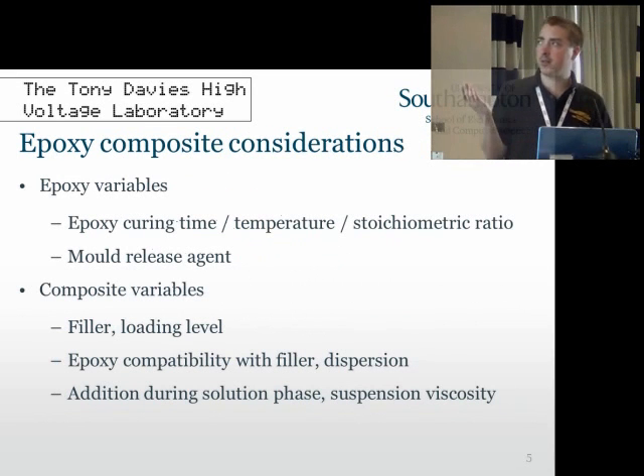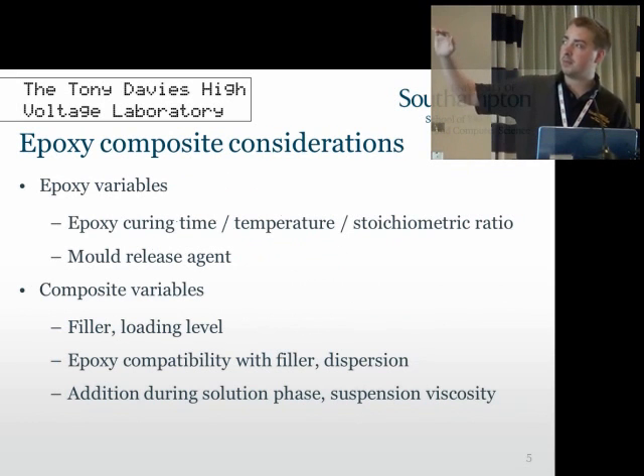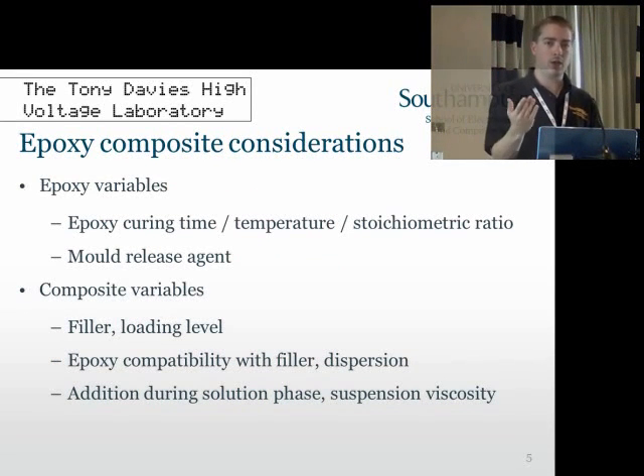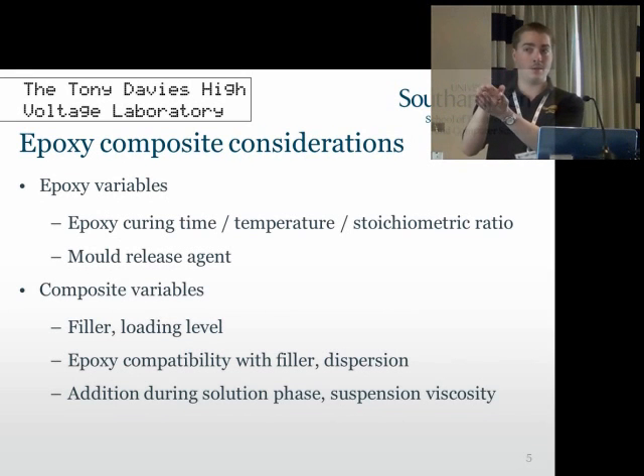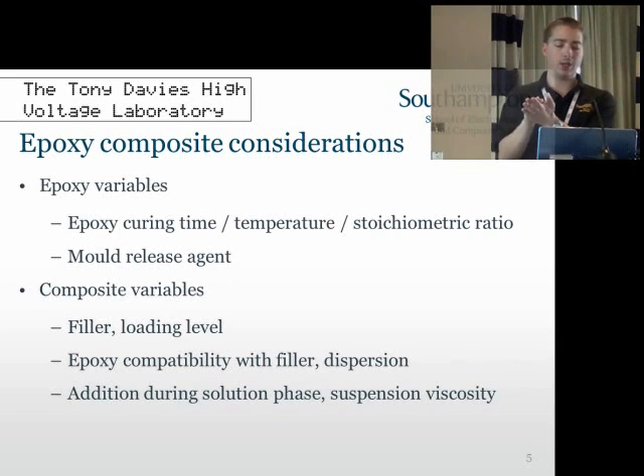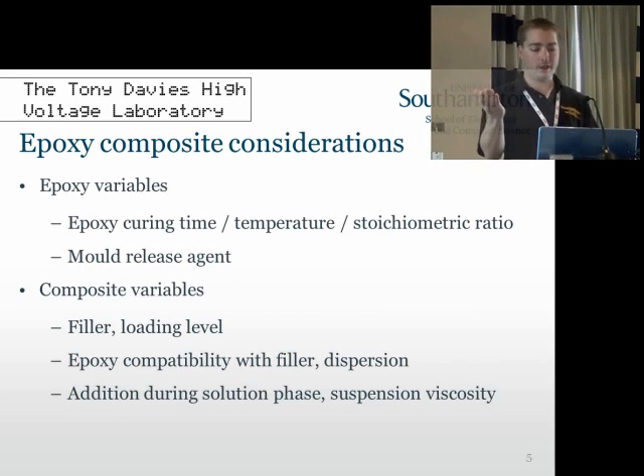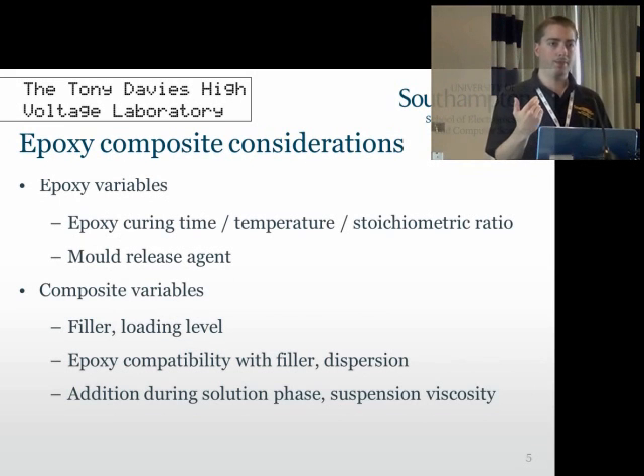Okay, so there's quite a lot you have to consider when you're making epoxy composites, some of which have already been covered, but I'm just listing them here. The curing time, the curing temperature for your resin and hardener combination, as well as the ratio between the two, as well as whether you use moulds to create your samples. Just think of a jelly or a jello mould, pouring your resin in and curing it with a hardener. It's often difficult to release it from the mould, so you have to consider any release agents or release films you use and the effect that this might have on your material. And then your composite variables will be the filler you choose, the filler loading, the filler size, the compatibility with the epoxy when you add it into your system, and how well it holds its suspension. So there's a lot to consider when we're making these materials.